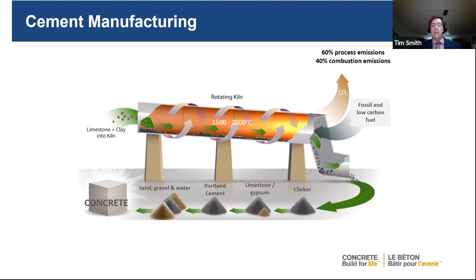The clinker is then collected. It's then for general use cement. Up to 5% limestone is ground back in with the clinker, along with gypsum, to create what's called Portland cement. You then take the sand and coarse aggregates, the water and the cement, and that creates your concrete. So the big thing is that your CO2 is created through creating the clinker itself, and through the combustion process, where you normally have either coal or natural gas as your source of fuel.